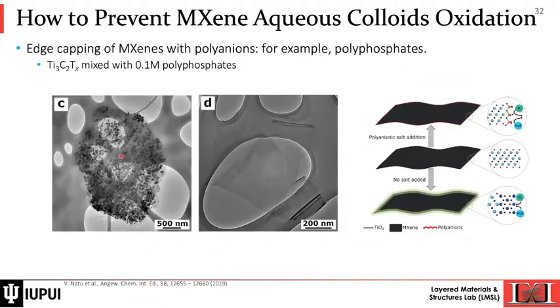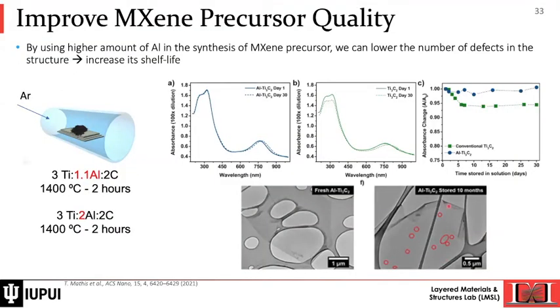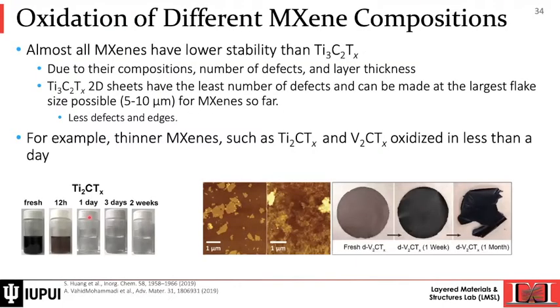You can see this is something expected after a few days of regular MXene, and this is what happens if you use the excess aluminum route. So a clever way to modify the precursor, something that almost no one expected to happen, but it's really working very well. Now, all of these that I mentioned were all about Ti3C2 stability.